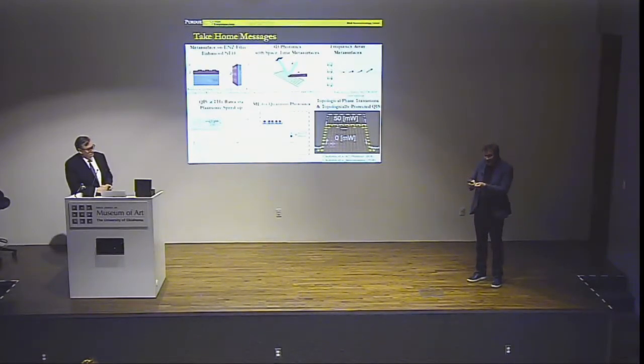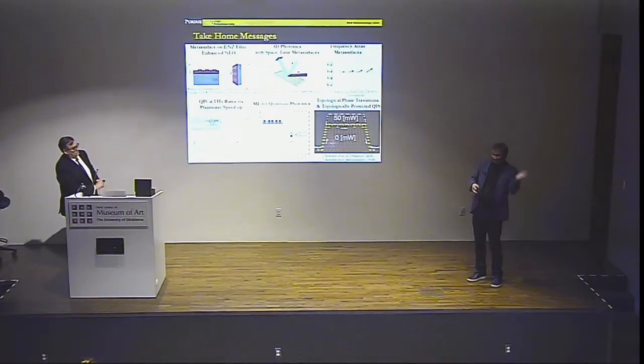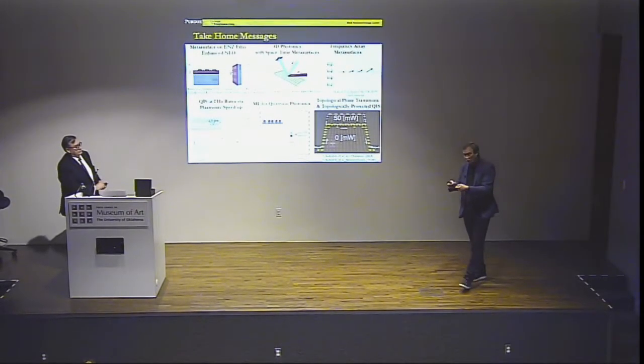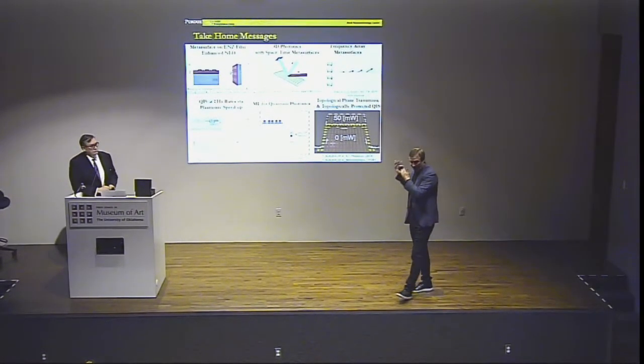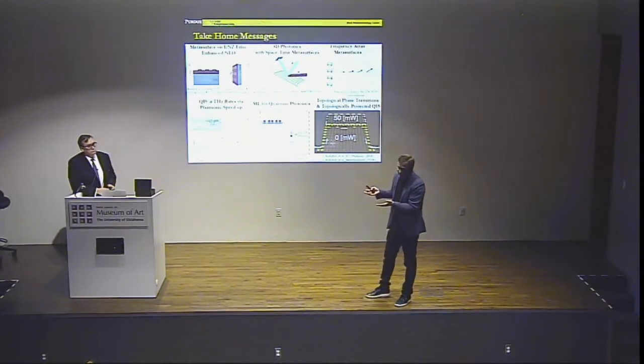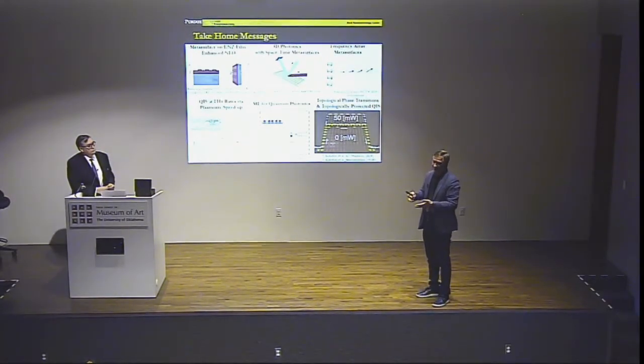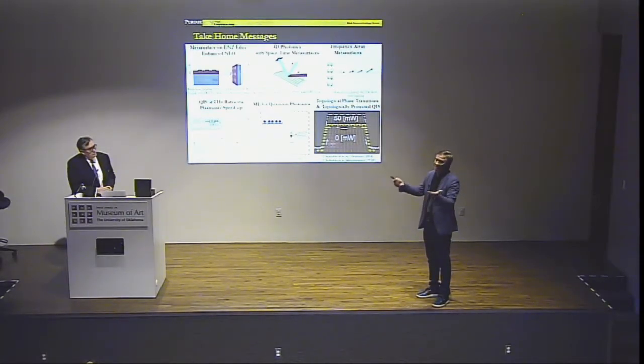The closer the antennas, in principle, the better coverage, the better sweeping. But the challenge in this case is that you would have to go below the diffraction limit. We use diffraction-controlled metasurfaces. Therefore, we're basically limited by the wavelength, and in our case, the spatial separation is just a fraction of the wavelength, let's say half the wavelength. But that works good enough.